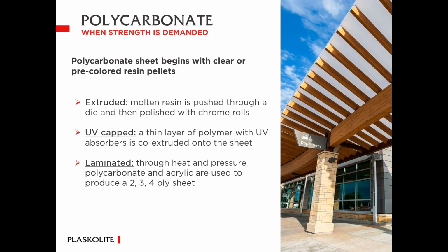The material itself is UV stabilized, so it can see some UV, but if you're going to have it in an outdoor application, you really want to put a thin layer of a UV cap on it to absorb the UV, and it's co-extruded into the sheet, which means that the product actually is chemically bonded in there, so you can't wipe it off or rub it out. It's actually part of the sheet, so it's a UV cap, and you can get that on 1 or 2 sides. Another thing that you can find with the polycarbonate is that it can be laminated.